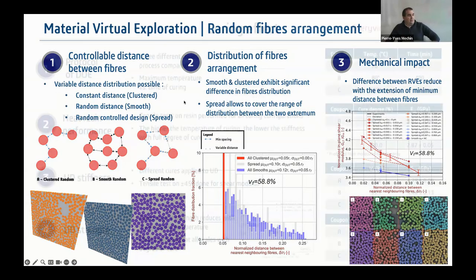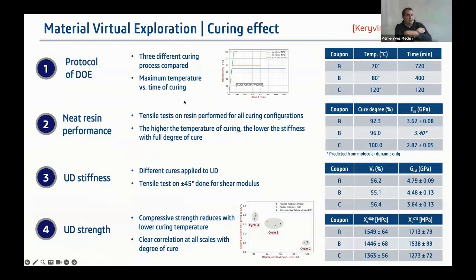Well, so I've been talking a lot about microstructures, RVEs, and components. To extend where we go now is the fact that we have an effect of the curing process. So we've been doing some testing where we have different cures. The different cures lead to different degrees of curing for the resin system. And we are able to introduce the resin properties into multi-scale models to see if we can understand the effect of the curing on the defects that we get at the end.